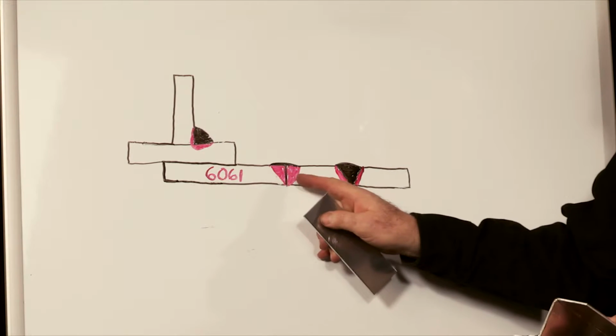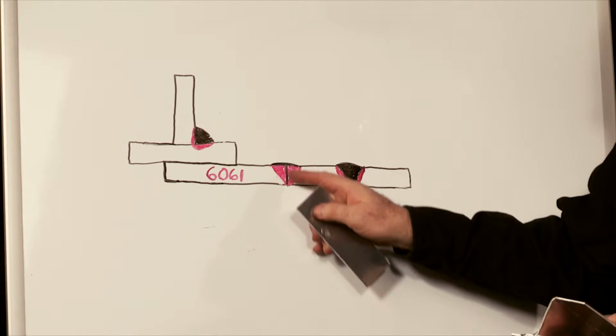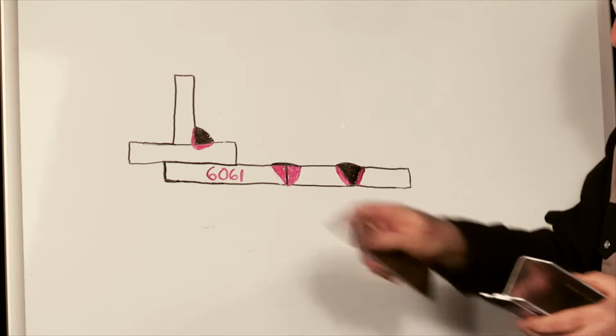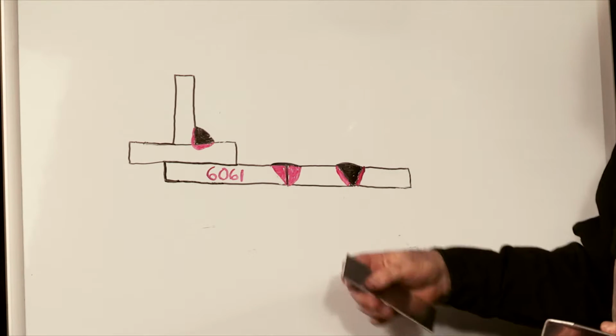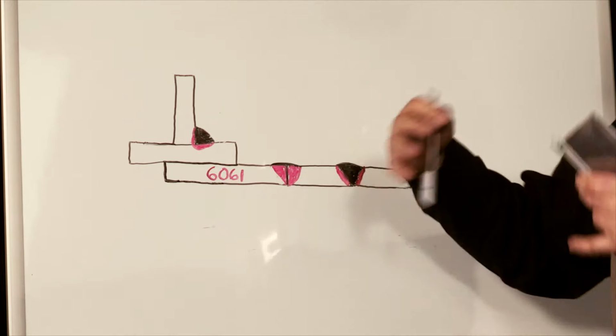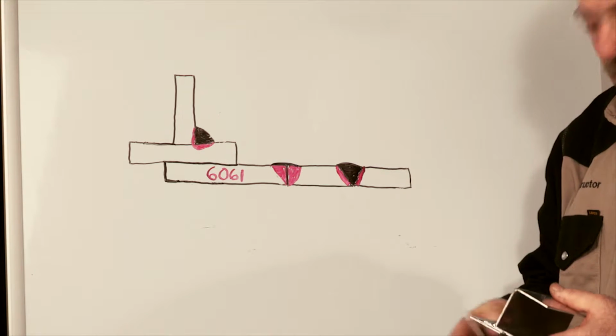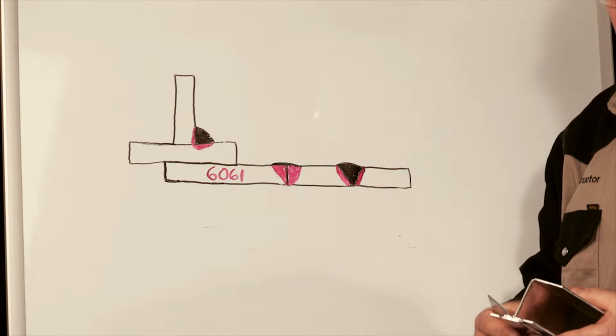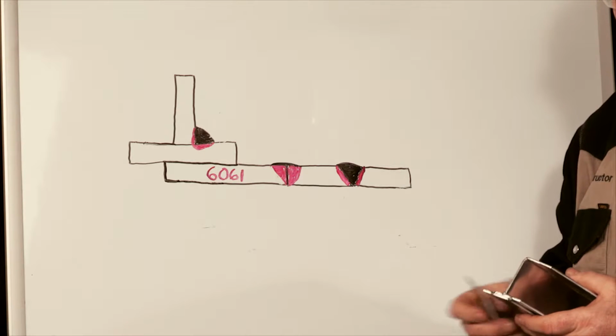This pink area here you see is the base metal, and that little gap, the black area, is the two pieces where they're butted together, and we add a little bit of filler metal on the top. And as you see, the composition of that weld, when all that metal is mixed together, is going to be more base metal than filler metal.